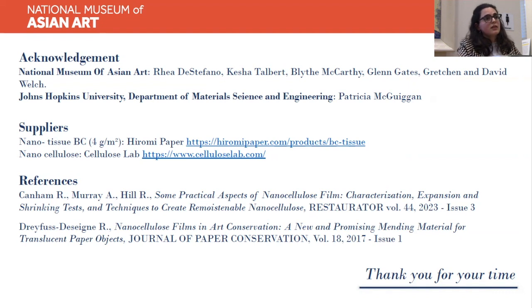I have a question about how compatible the two materials, parchment and nanocellulose, are in terms of fluctuating humidity. The parchment is very reactive. Are they compatible in terms of their physical properties with adsorption and desorption of water, fluctuations in relative humidity? Yes, actually, compared to paper, nanocellulose looks much more like parchment. It is very reactive. That's why we couldn't apply the adhesive directly by brush. So they look very similar also in how they respond to humidity.